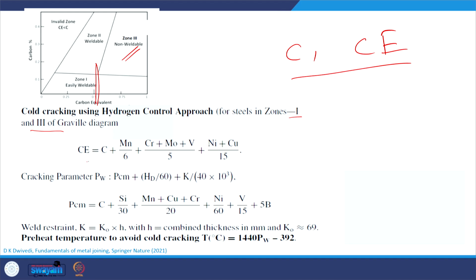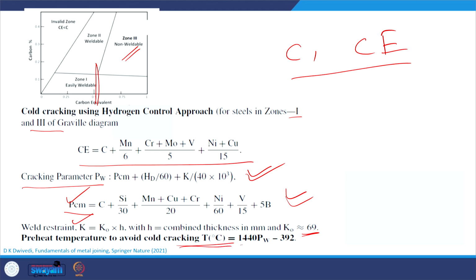So, if we see the carbon equivalent calculated using this equation, then we have one cracking parameter which is calculated using this set of equations, and we get one PCM which is calculated using this equation. And then weld restraint is also considered, where K naught multiplied by H, H is the combined thickness in mm and K naught is a coefficient. So, using these various parameters PCM, K naught, we can determine the preheat temperature to be used for avoiding the cold cracking. Now, I will summarize this presentation.